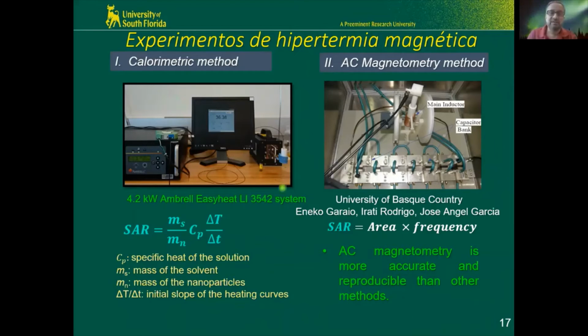So we have our nanoparticles, and I'm going to show you some nanoparticles in the next few slides, the kind of anisotropic nanoparticles that we make. So we put these particles inside the inductive coil here. That's the AC power supply. It's a commercial one. Remember that we need to have large amplitude, high frequency power supplies. Most of the AC power supplies, the amplitude they produce is very small. So we need much higher amplitudes here. Okay, I'll give you the numbers in a minute.